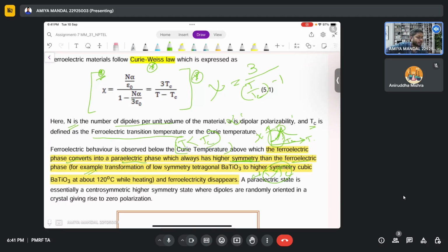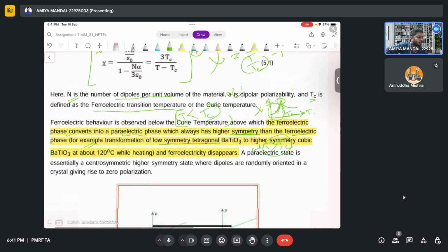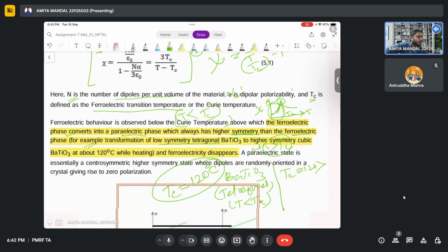For example, the transformation of low symmetry tetragonal barium titanate. Barium titanate has tetragonal symmetry at T less than Tc. Its Tc is approximately 120 degrees centigrade. For T greater than 120, it shows a cubic structure, and cubic is more stable. So this case of transition is also seen in barium titanate. Barium titanate is a pure perovskite material, which has an ABO3 structure.